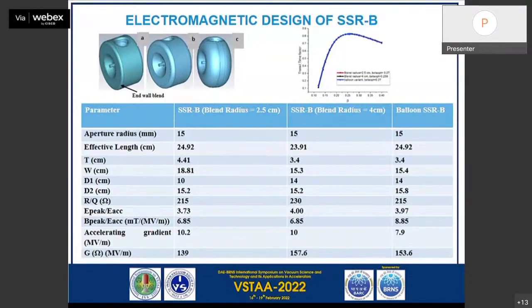We have performed electromagnetic design of 3 SSR cavities at geometric beta of 0.21, and 2 are conventional SSR cavities. And you can see the first one with a blend radius of 2.5 centimeter, second with 4 centimeter, and the third is a balloon shaped resonator, which is well known to reduce the multipacting effects. But as can be seen in the table of parameters, the accelerating gradient supported by the balloon spoke resonator is the minimum, 7.9, because the peak surface magnetic field is the largest for this.